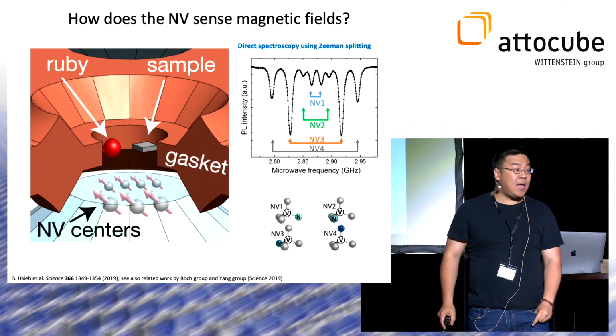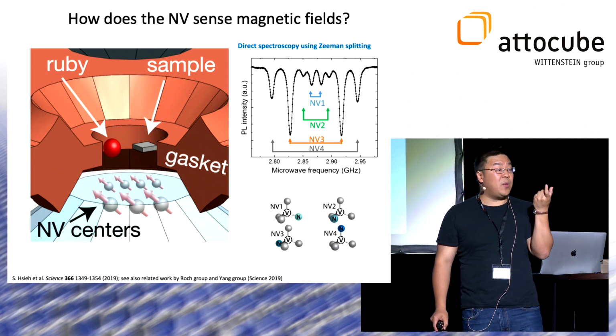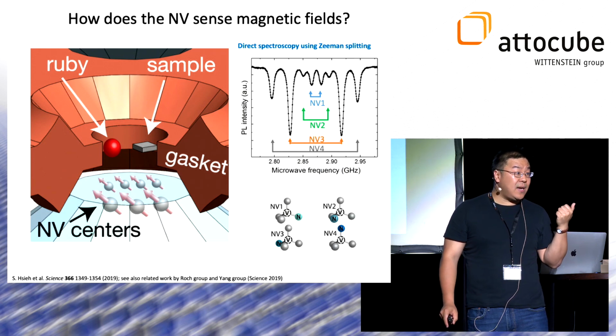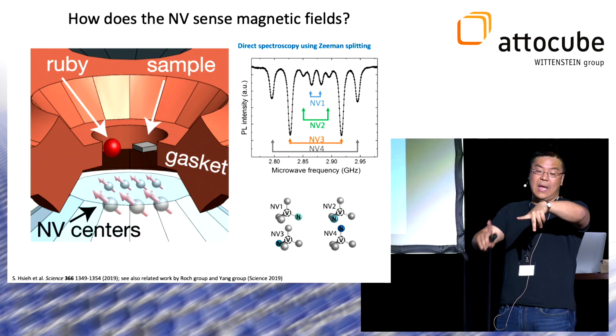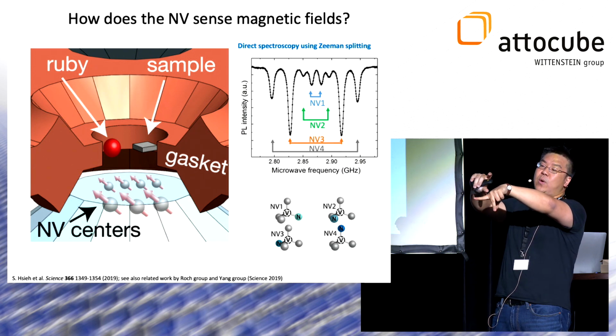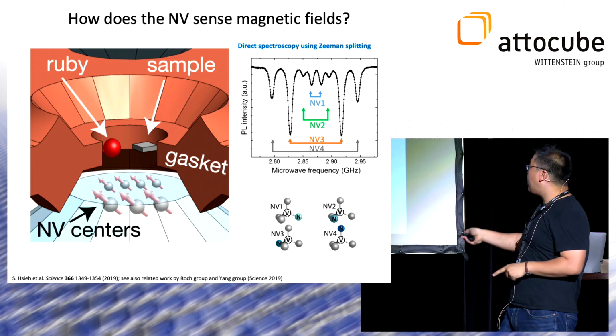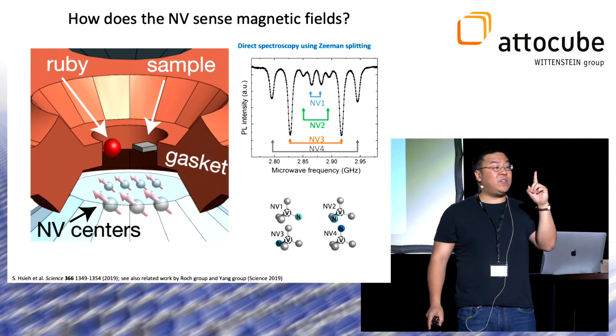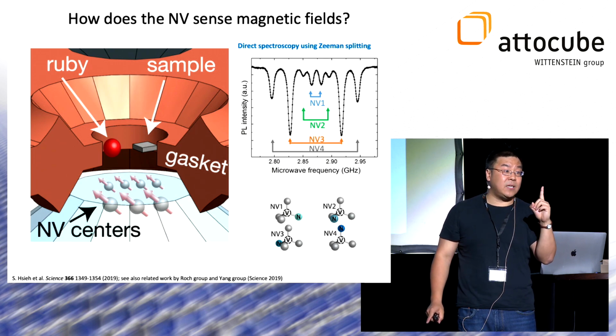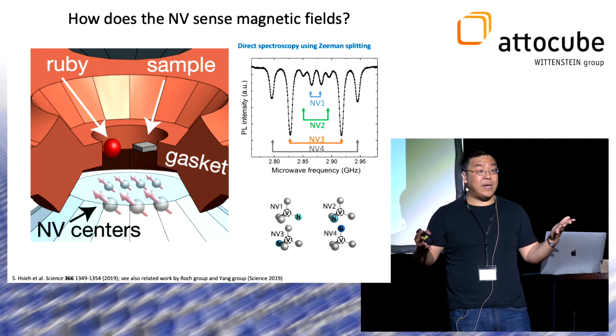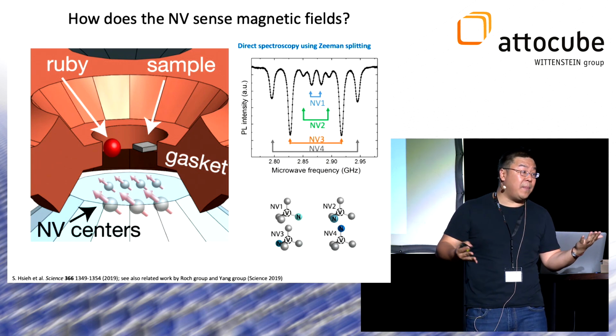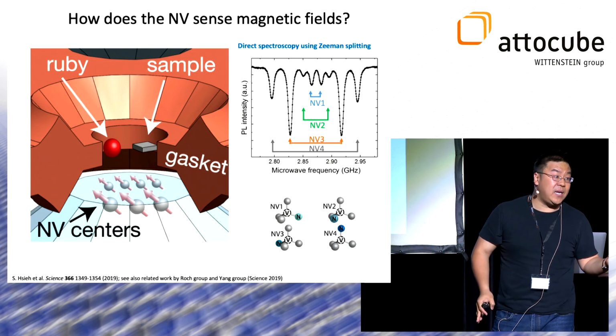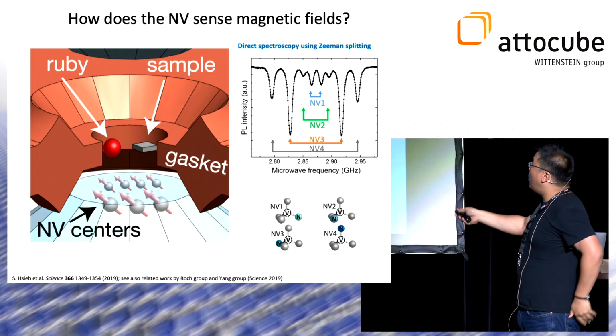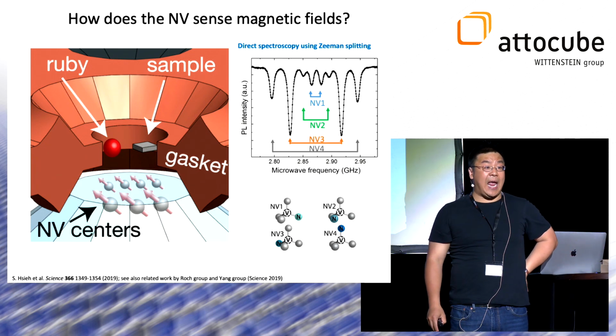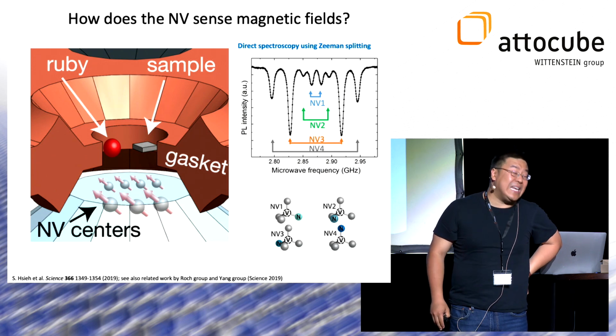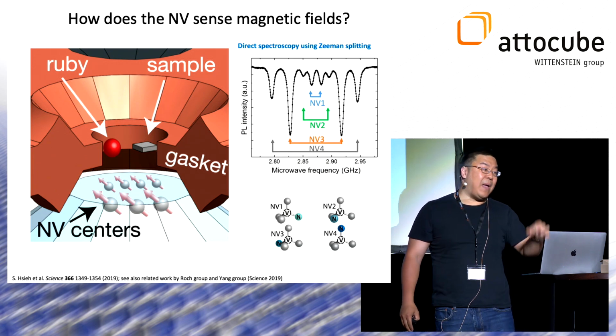It turns out that the signals we'll typically see in an actual experiment look like this. These are magnetic resonance lines, but instead of the pair of lines that I showed in the previous slide, you end up seeing 8 different magnetic resonance lines. This can be easily understood. Diamond has tetrahedral symmetry, which means the nitrogen vacancy axis can be along any of 4 directions. Because you're most sensitive to the projection of the magnetic field along the NV axis, if you have an ensemble of NV centers with different orientations and a generic magnetic field that doesn't point along one of them, you will have 4 different Zeeman splittings corresponding to 8 different magnetic resonance lines. So from these 8 lines, you don't just get a magnitude, you immediately get a vector magnetic field, an orientation of the magnetic field at a local spot as well.